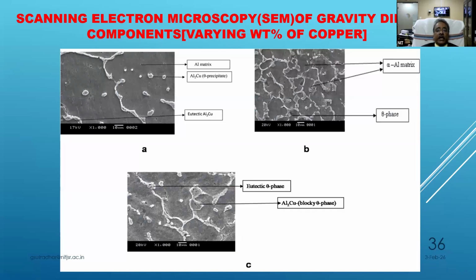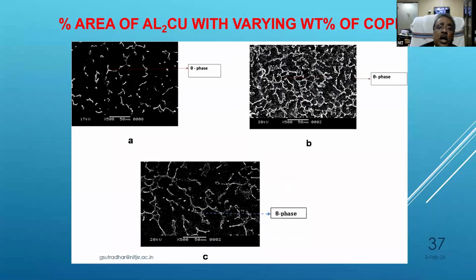This is another one, a scanning electron microscope image of gravity die casting, showing how things behave under different conditions. See, it is only 4%, where the theta precipitation in the grain boundaries is like this. When going from 4 to 8, the precipitation of the theta phase increases, and in between is the alpha aluminium, pure aluminium. It increases again when the percentage of copper goes from 8 to 12%. So it varies with the percentage.